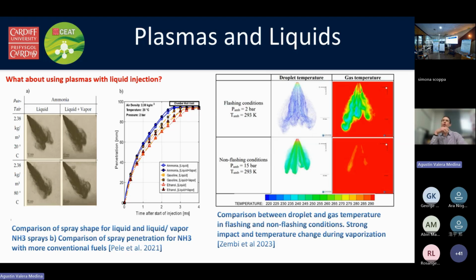And as part of that, some of the studies that have been ongoing, we included, analyze what happens when you have ammonia being injected. And depending on the pressure, going back to the pressure, if the pressure in the atmosphere that you're injecting into is not high enough, you might have flashing conditions. So you will have the spray that eventually will vaporize, but because it's cold enough and then reaches that point of balance between the liquid and the vapor, it will start producing liquid again.